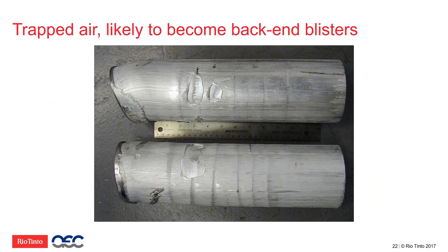Now the air can be trapped also at the billet surface. That's coming from perhaps damage on the delivery or the loading of the billet in the press, or of course any kind of buckling that could occur on the billet during the upsetting phase. It's very true if you are running long billets, let's say about 50 inches or so. When that billet is put under pressure and starts filling the liner inside the container, then of course buckling can occur and that air entrapment can be generated.